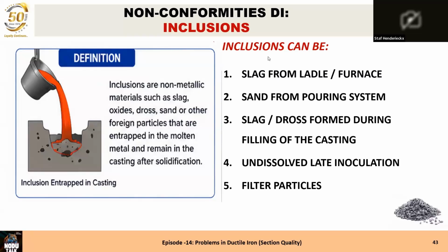It can be sand from the pouring system due to the high pouring speed and due to the high metal speed inside the pouring system. It can be slag or dross formed during the filling of the casting. We have seen it. Dross is nearly always present in ductile iron, because dross is the combination of magnesium, silicon, and oxide, and it will always be there. Sometimes you can have undissolved late inoculation, and on the other side, what I mentioned already, filter particles.